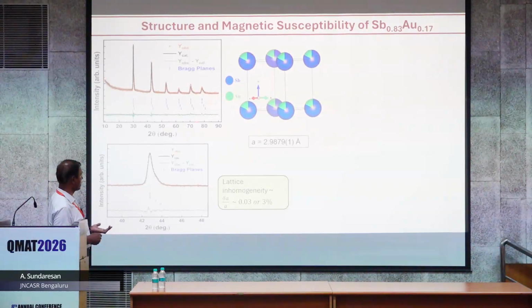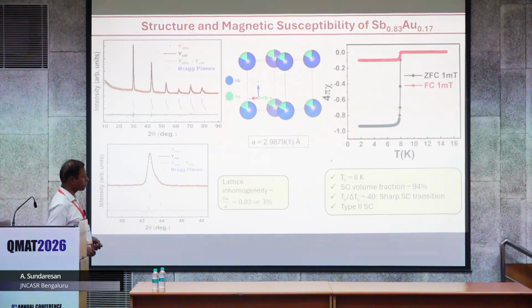On the higher angle side, indicating inhomogeneity or strain in this sample, which is very obvious. You apply this metastable phase from rhombohedral to cubic phase, which obviously is not a very stable phase. So you have a lot of strain, and even chemical inhomogeneity in this, and then the lattice parameter is close to 2.98.